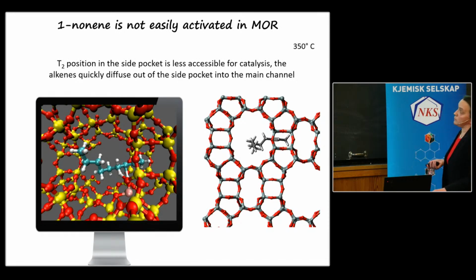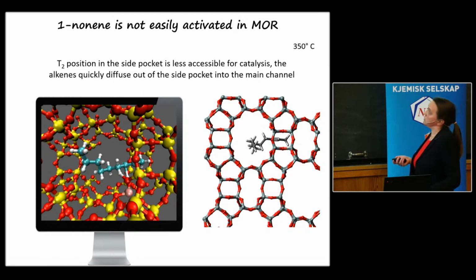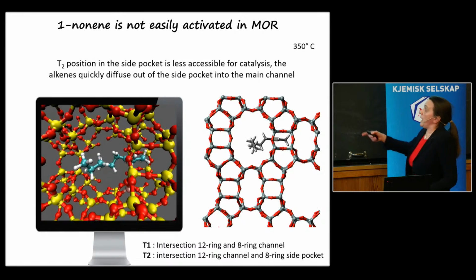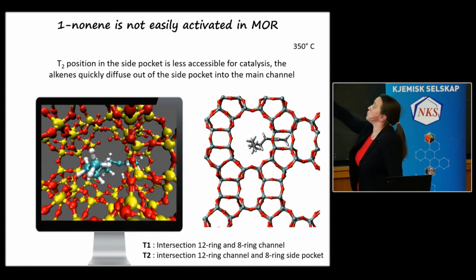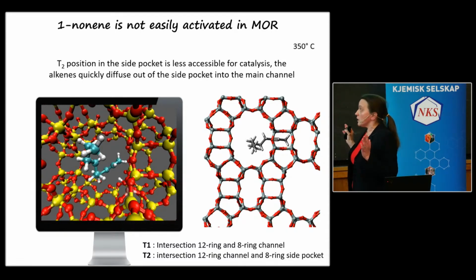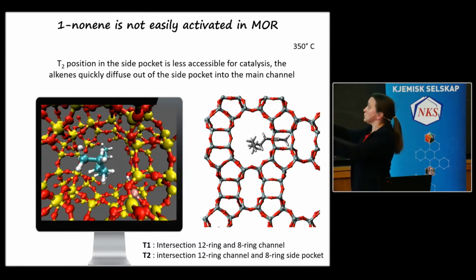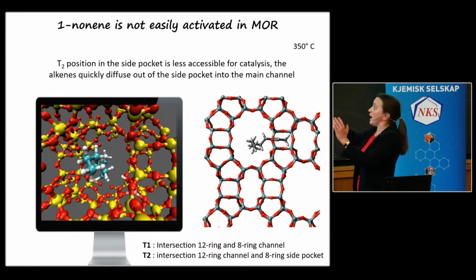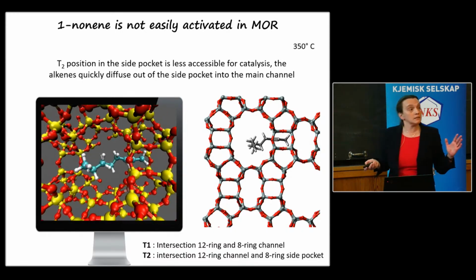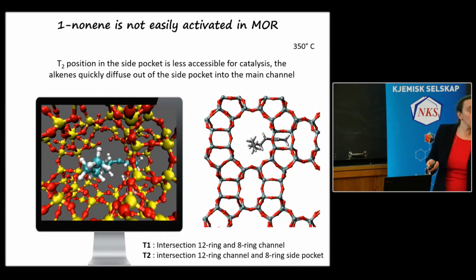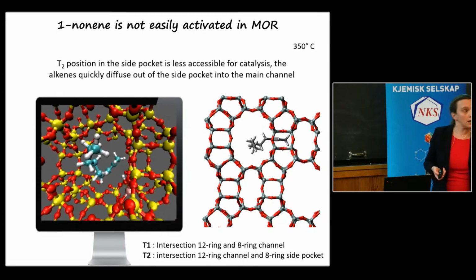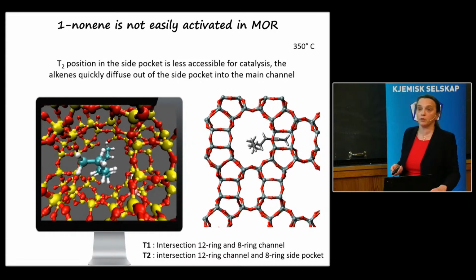So what we did then, we did some of these MD simulations, and this is in mordenite. Here you see nonene. And what we can see, it starts somewhere in the side pockets, and then when the simulation proceeds, we can see that it's not active. It just goes into the 12-ring straight channel, and it stays there. It's completely inactive. Yeah? So it will not form an aromatic species afterwards because it's not activated in mordenite.